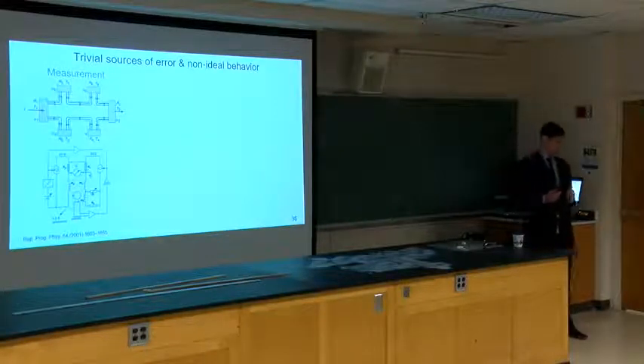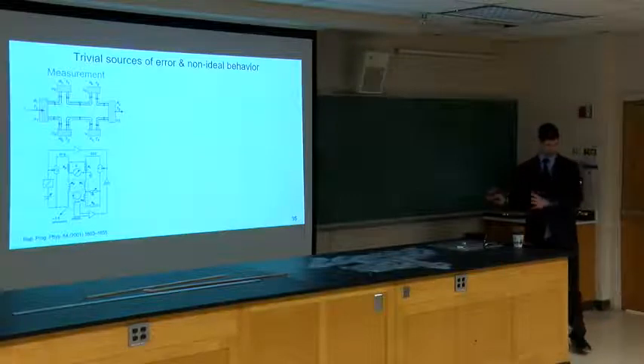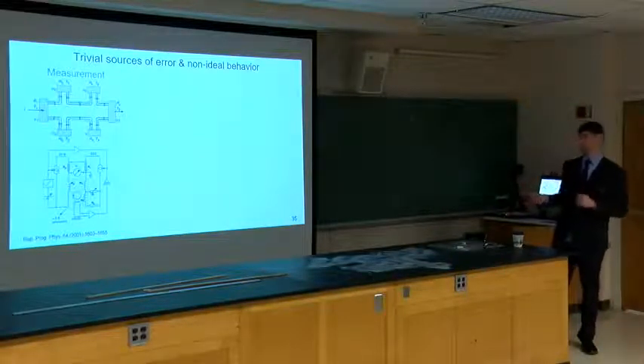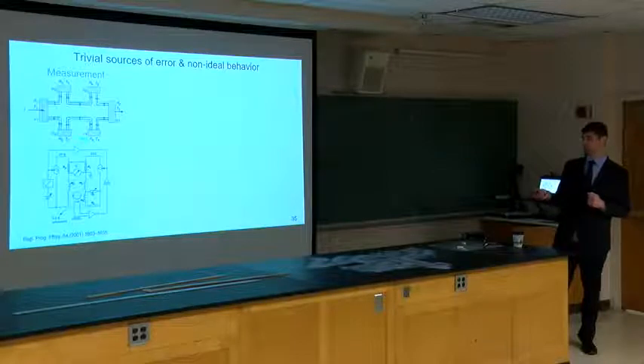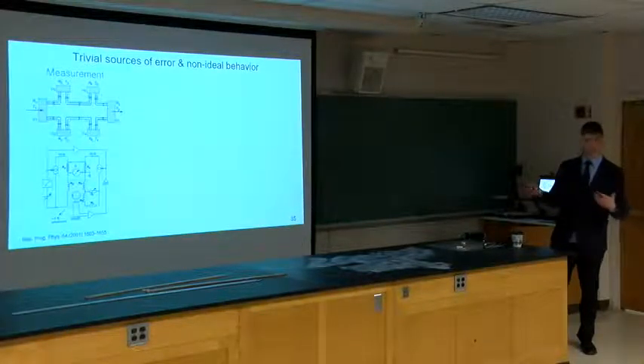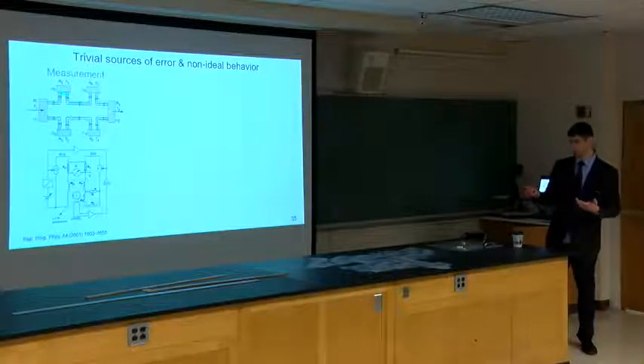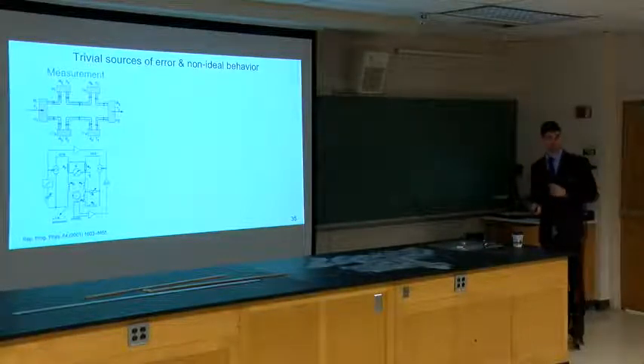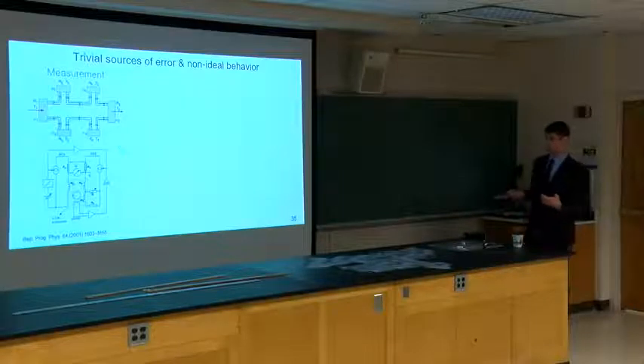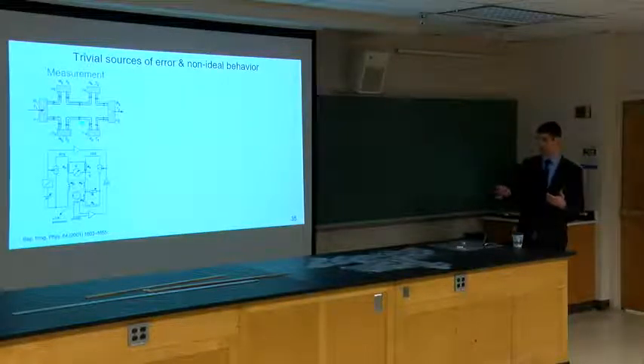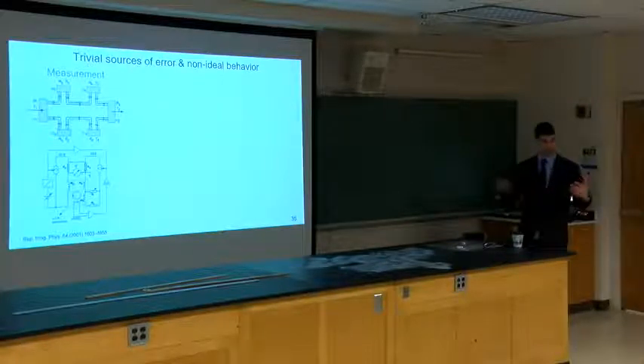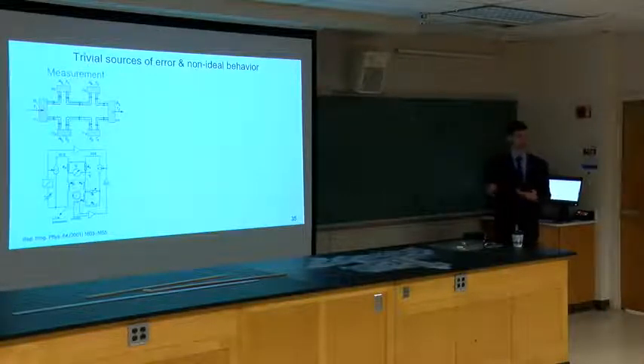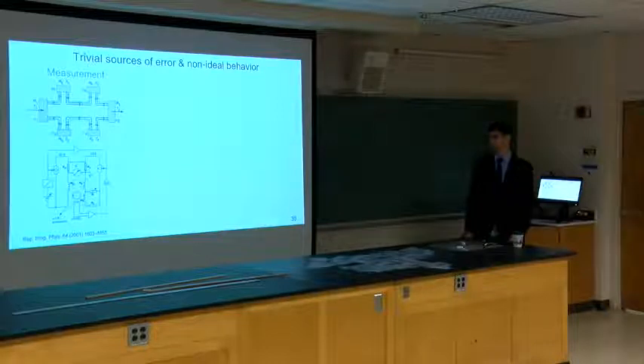Well, if we want to analyze this, we first need to understand what the trivial sources are that we can just remove and not have to consider. First is measurement. Depending on how you measure the voltage probes, if you're applying current across the system here, with a very large magnetic field, so you're firmly in the quantum Hall state, you measure the resistance on this side and compare it to the resistance you measure on that side, you can actually get a difference of 10 ohms. And it all has to do with the Hall voltage. Because if you have a Hall voltage built up across here, and the impedance of your measurement circuit is lower than, let's say, one resistance quantum, which is 25 kilo ohms, then it's fairly reasonable that you can have an error of about 1 out of 1,000, which would be single-digit ohms.